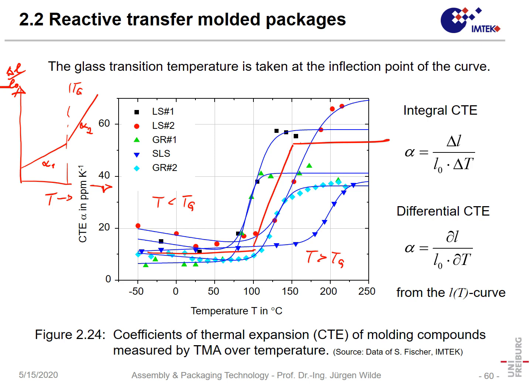And for the CTE, we can also say we have two possibilities how to define it, and that is important for when you take CTE values from literature. One is the differential CTE. That is just the slope here. That's a differential. On the other hand, we also have an integral CTE that is also given often. So for instance, people say we start at that temperature and we take the CTE as the integral slope, and that would be the integral CTE. And I can warn you, do not mix this up.